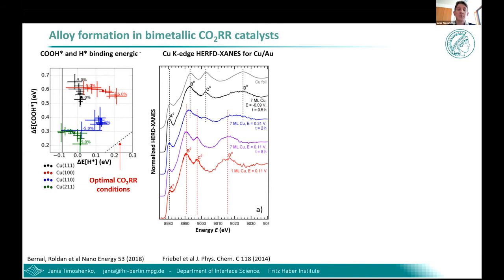And in this particular case, XAS gives us a lot of important information because both XANES and EXAFS regions of absorption spectra are actually quite sensitive to interatomic distances. For example, it was demonstrated in this study by Friebel, where copper monolayers on a gold substrate were investigated under applied potential, and in situ formation of copper-gold alloy was detected.